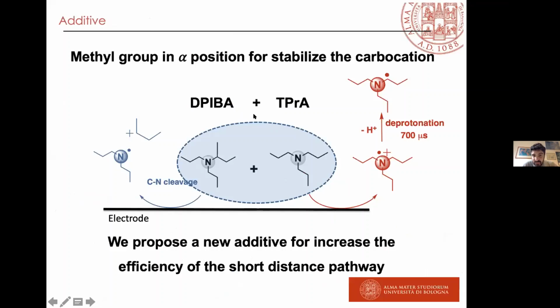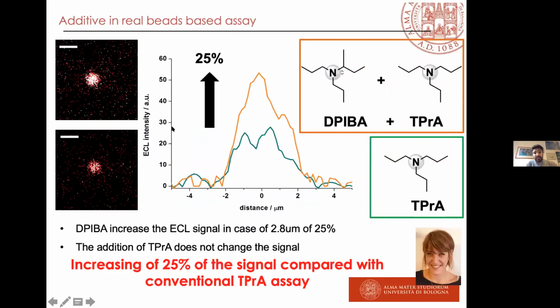So we add to the classical TPrA solution, so classical tripropylamine solution, an amine with a methyl group in the alpha position. We put a methyl group in the alpha position in order to stabilize this pathway, to stabilize and highlight the pathway very efficient in the short distance. So we use this as an additive, and we mix it with the TPrA, and we come back to our surface generation beads emission mode.